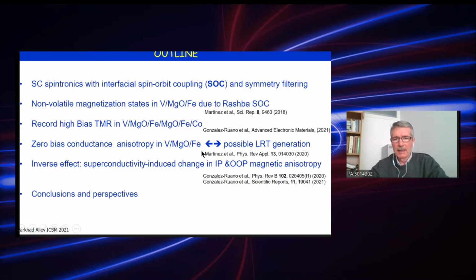The proof of presence of long-range penetration was initially indicated in a publication studying zero-bias anisotropy of the conductance. Recently, in two further publications, we also found changes in in-plane and out-of-plane magnetic anisotropy induced by the superconductivity.